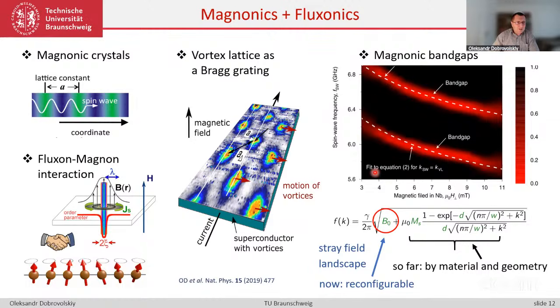And here, this is just an example of one dispersion relation for magnons, because it depends on the mutual orientation of the applied field and the propagation of the spin wave in the material. But this is just to highlight that so far, the typical parameters which affected the dispersion relation were width, thickness, and saturation magnetization of the magnonic conduit. So basically parameters which are defined and then kept constant during the operation of a magnonic device.